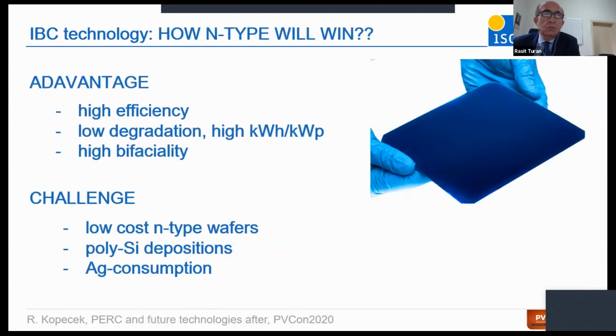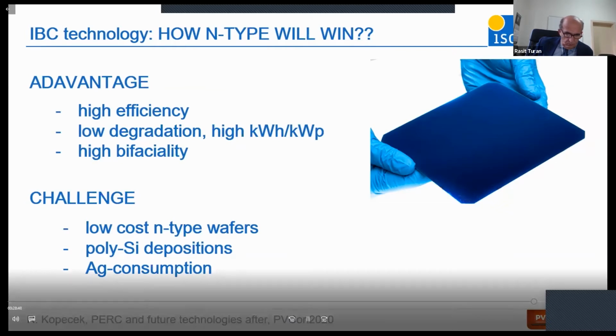So now my final slide about advantages and challenges in N-type. So the advantage is that, of course, you can have high efficiency and low degradation because of no LID, LETID, and for example, also if you take care of potential induced degradation in the module, this can be gone. In addition, you have a higher kilowatt hour per kilowatt peak performance because you have a better low light sensitivity and also high temperature performance because of the higher voltage. And also you can have a very high bifaciality, but the challenges still remain to be as cost effective as PERC. So for example, low cost N-type wafers and still polysilicon deposition if you go for poly IBC, and the major challenge is the silver consumption.